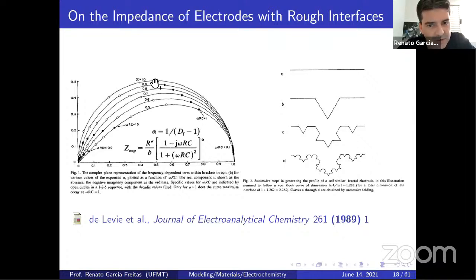For alpha equal to 1, which is ideal for sure, we have a perfect semicircle, located here at 0.5. And as alpha decreases, alpha being 1 divided by the fractal dimension minus 1, and the impedance values, the alpha from the Brug equation further: 0.9, 0.8, 0.7, 0.6, 0.5, and we have almost a depressed semicircle. And as soon as we decrease, if you take a look at de Levie in 1989, we see the 45 degrees down there, because if we decrease the pores, it becomes rough, it becomes porous. So if you take a look at high frequency down there, you see the 45 degrees of impedance.